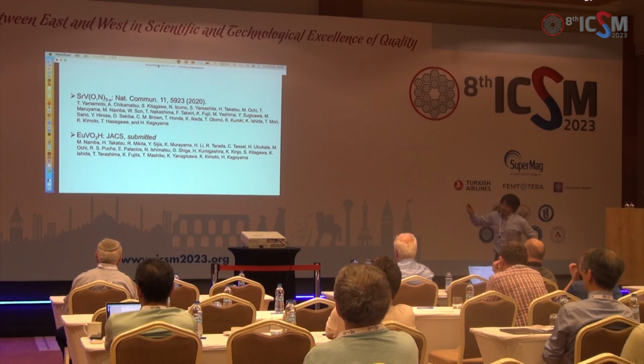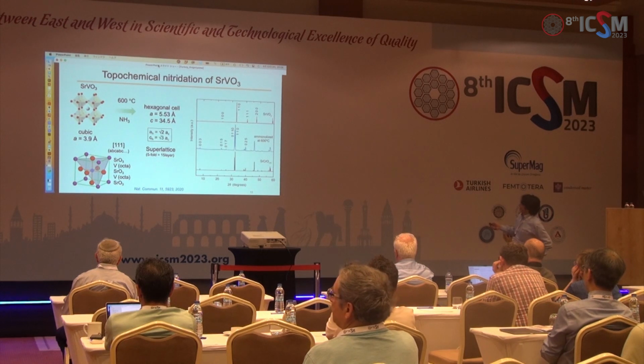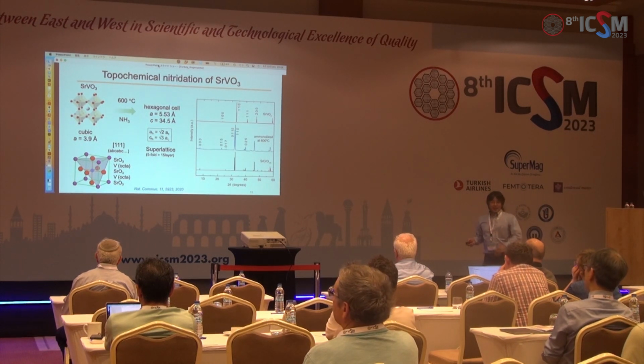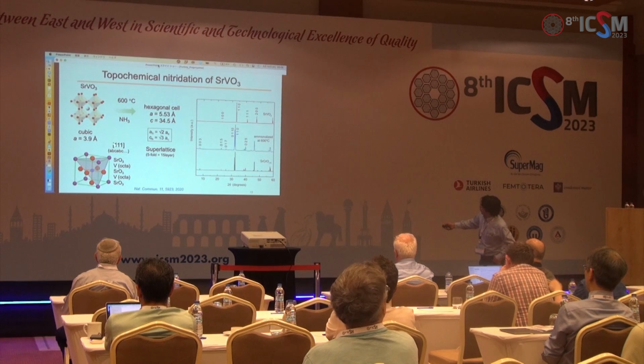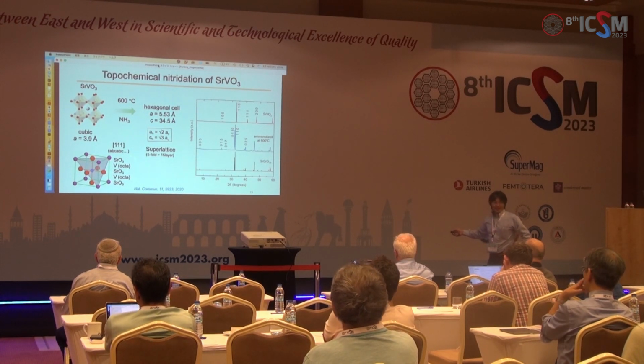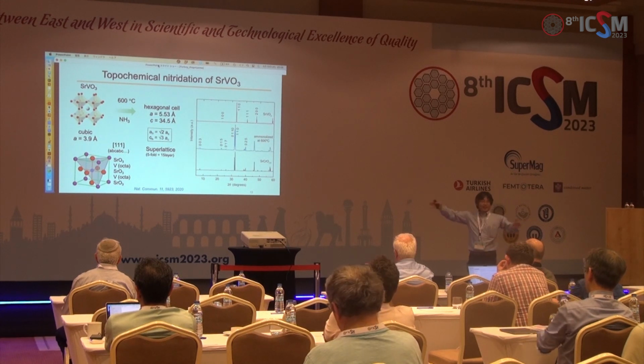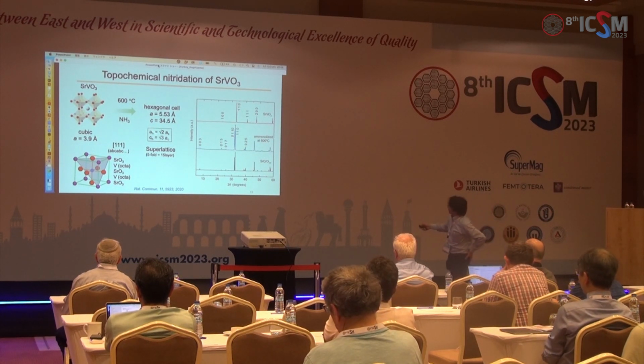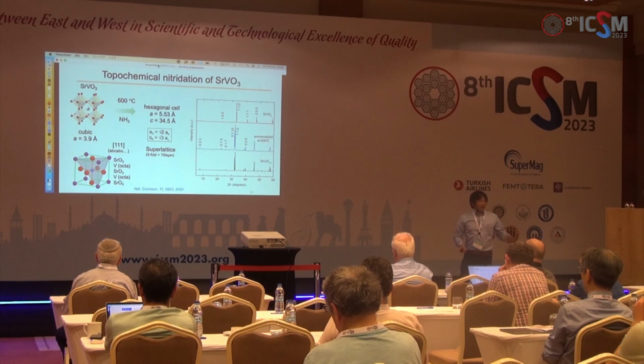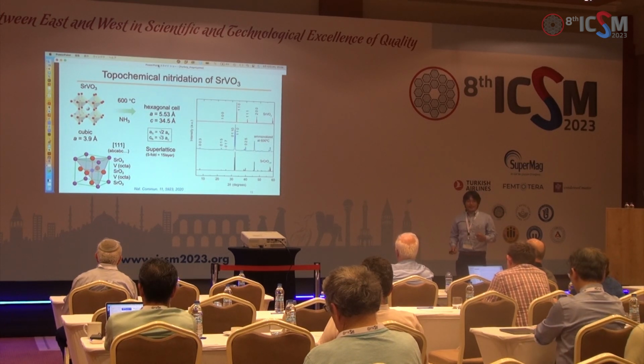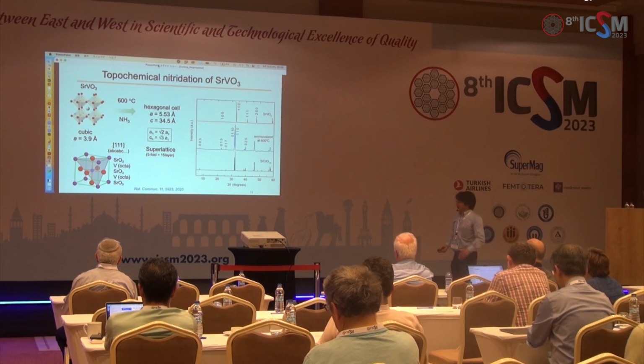So for the first one, this is oxynitride. What I did is topochemical reactions. Okay, I use ammonia in this case. I do a topochemical reaction starting from this SrVO3 powder, and in this position we got this parameter. So the c-axis is highly elongated, and I found that this is described by these things, and now we found the superstructure formation along the 1-1-1 direction. Okay. Something is happening structurally or compositionally.